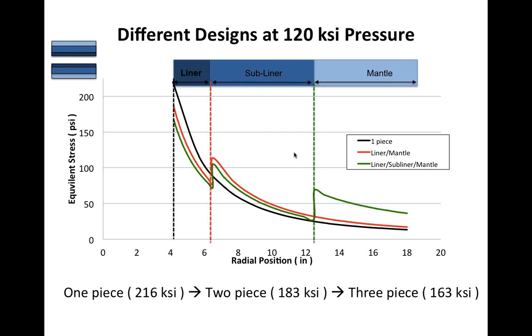So the biggest factors here are pressure and also length of the container. Today, containers are getting much longer. In these long containers, we typically go with a 3-piece liner so we can control the deformation or mechanical expansion of the liner when we're in high pressure. Very often today when we go to long billets, we also go to high pressure. And the combination of high pressure and long billets means we have to have 3-piece containers.